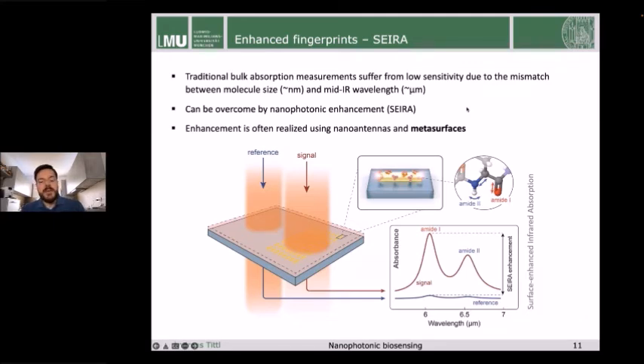So to improve the overlap and improve the sensing, again, we come to nanotechnology. We employ optical nanoantennas to focus the mid-infrared light into tiny hotspots of the electromagnetic fields, as shown here. And the nice thing is that these hotspots are now on the same order of magnitude in size as the molecules that we want to detect. So we get a very large interaction cross-section, and we can really boost the signal from the small molecules on the surface. This is just a sketch here on the bottom right, where you see the reference, which is without the antennas, where you see only a tiny modulation by these molecules, and we bring in the antennas, and then we have a large enhancement allowing us to detect these characteristic amide I and II bands of the proteins that we want to detect here.